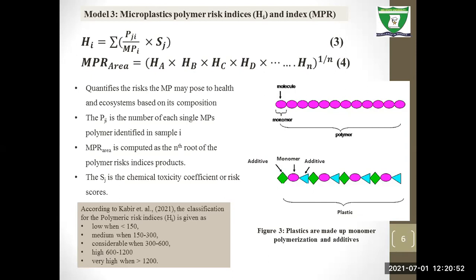If you have 10 microplastics and maybe 3 are polypropylene, then for polypropylene you have 3 divided by 10, which is the overall, times SJ. The SJ is the chemical toxicity coefficient or risk score. How do you determine the risk scores? The study of Lithner et al. 2011 has provided hazard scores for different polymer types. So you have the PJI, the quantity of the particular polymer identified, divided by the total number of microplastics in that particular sample, times the risk score for that particular polymer. Some of the risk scores are presented in the next slide.